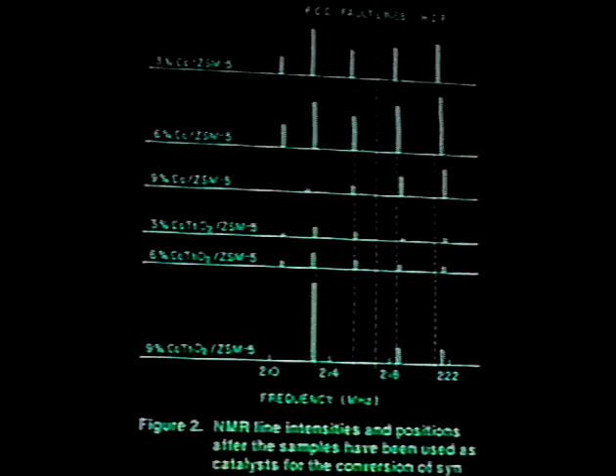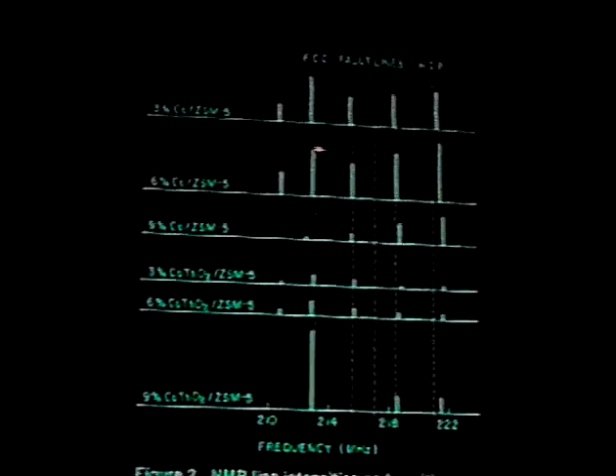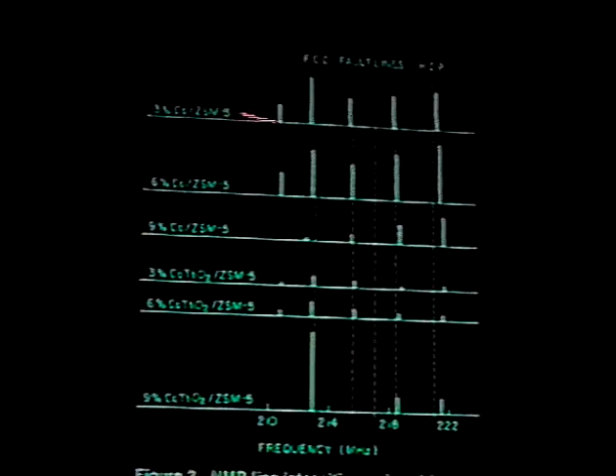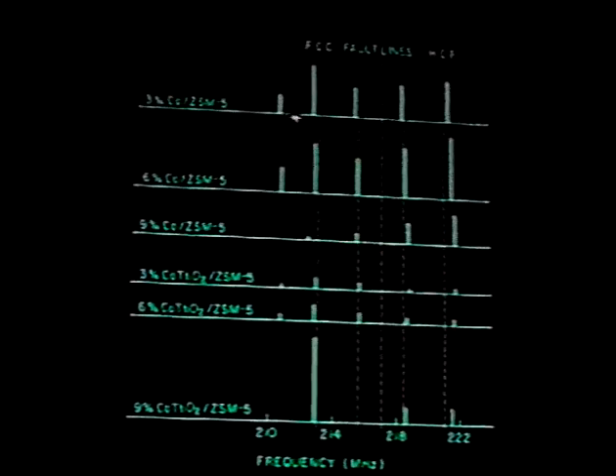Now, these samples were used in syngas conversion at 280 degrees for 48 hours, and the spectra were again studied. One thing we found was a somewhat of an increase in the intensities of the 3% and 6% cobalt, but the 9% cobalt did not show an increase. It actually showed a decrease in the line intensities.